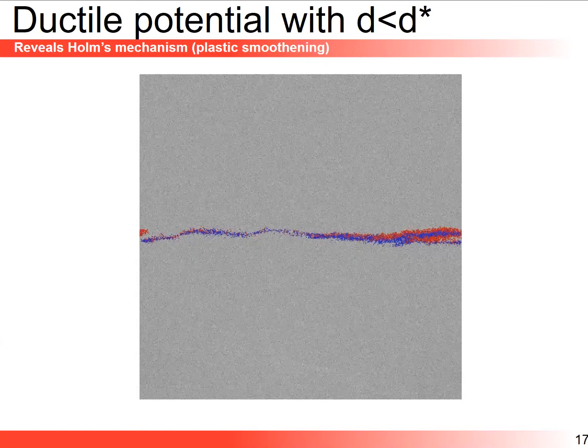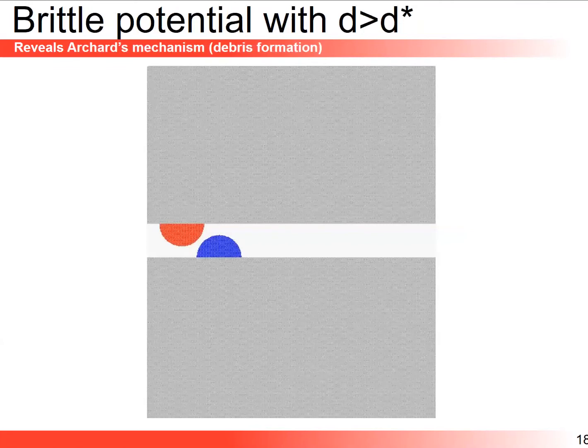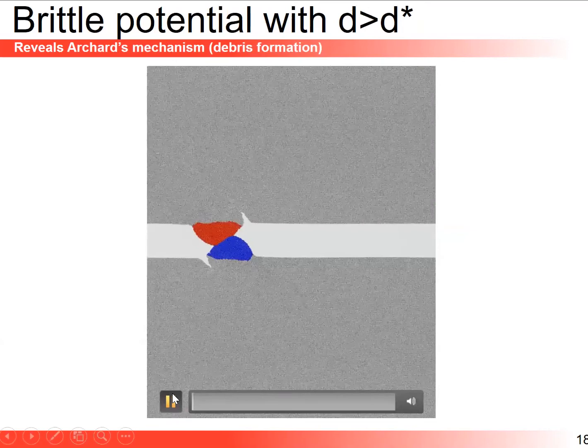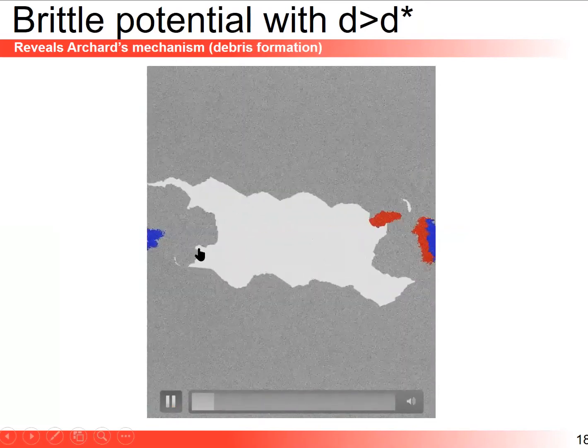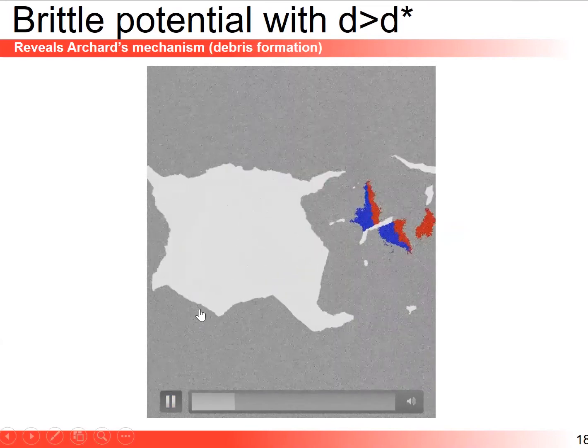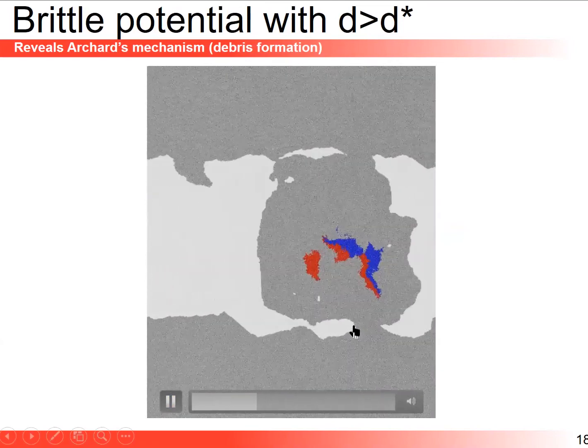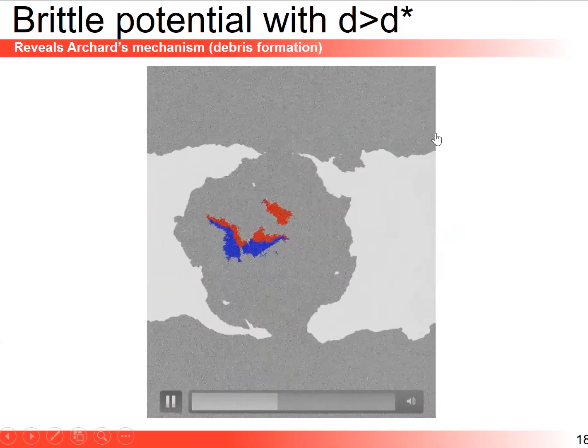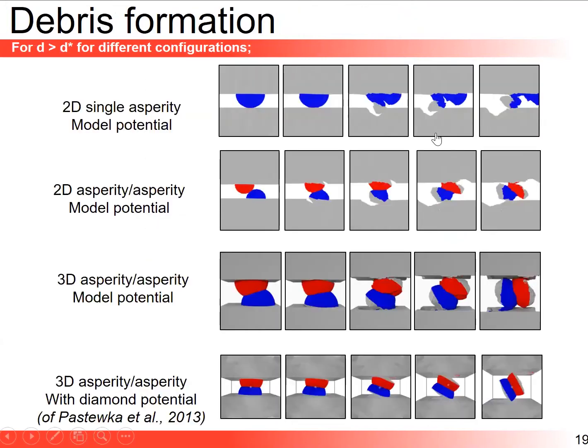Okay, so a lot of plasticity. We are ductile, but no debris formation. So now I'm not changing necessarily here the material properties, but we make the junction size D larger than D star, and something completely different occurs. We get cracks, and you see you start forming a rolling debris, which is incidentally creating a roughness. You don't flatten the surface. Okay? You have a debris with a well-defined size. Okay, so as I said, this has been repeated with more realistic potentials also in a 3D setting, and consistently what we have observed, if D goes above D star, we transition to forming a debris.